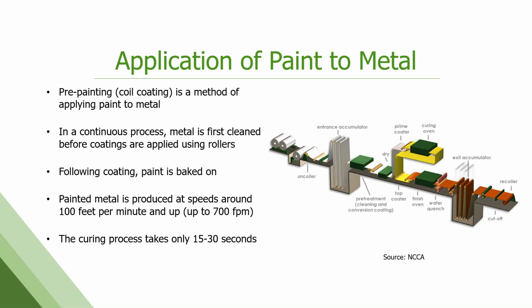Most of these paint lines are running anywhere from 100 up to 700 feet per minute, depending on how new they might be. The curing process for the paint, so the time the paint touches the strip until it is completely cured and dried, is anywhere from 15 to 30 seconds on average. So very, very fast. Very thin film too, which we'll talk about further in the presentation here.